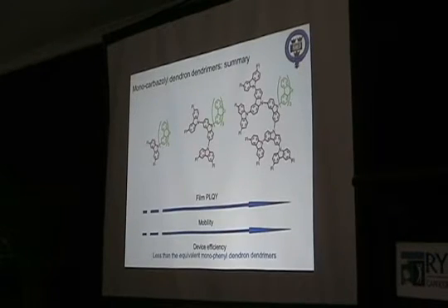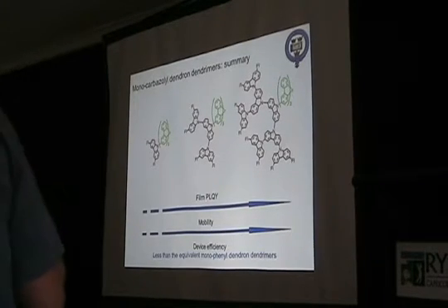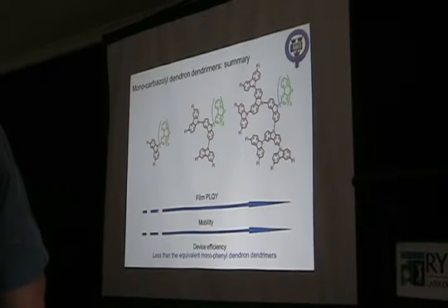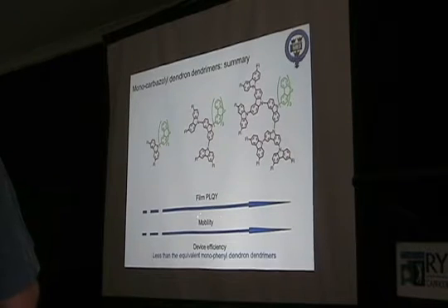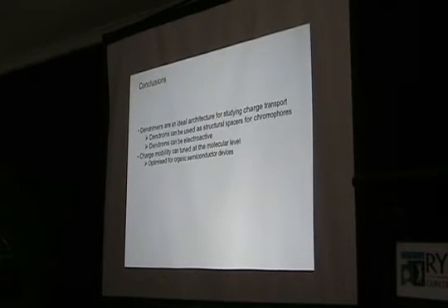So, summary. For this class of materials, as you go from first, second, third generation, film PLQY increases and the mobility increases, but the device efficiency is actually worse than the equivalent mono-phenyl dendron dendrimers.